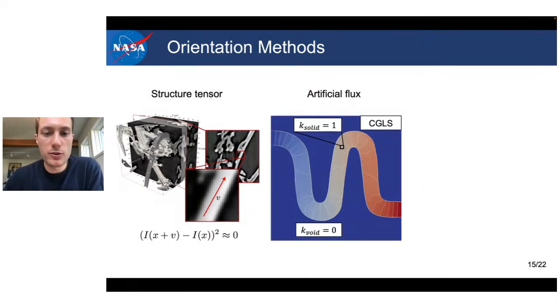Similarly, we also implement an orientation method using the conductivity solver. We basically imposed an artificial conductivity of 0 to the void phase and of 1 to the solid phase. We run conductivity simulations in a specific direction, and the heat fluxes that are generated at the end of the simulation after the solver has converged are going to be roughly aligned with your local orientation of the material as well.